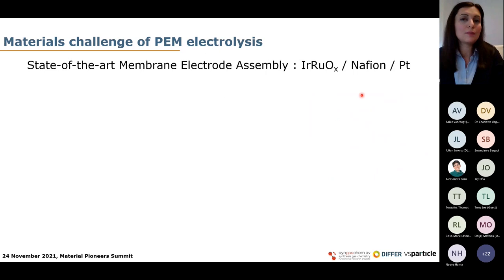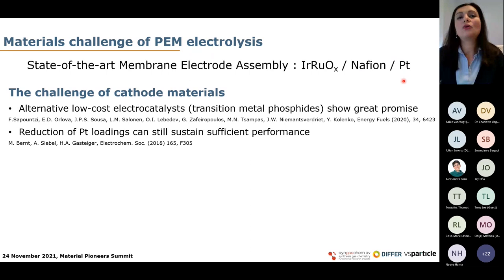The state-of-the-art polymeric membrane used in water electrolyzers is called Nafion, a material from Dupont with an acidic nature. This poses the limitation that PEM water electrolyzers rely on platinum group metals as catalysts. The cathode is the compartment where hydrogen evolution takes place, and this currently relies on platinum.